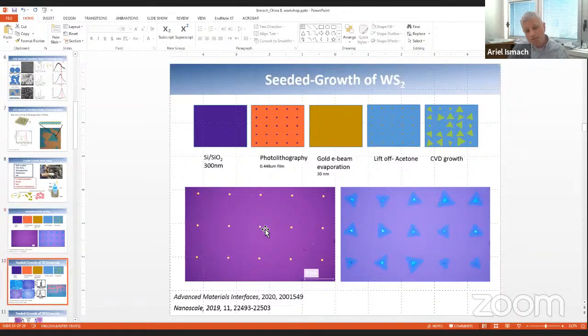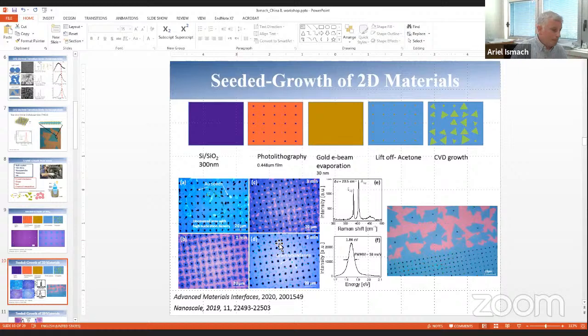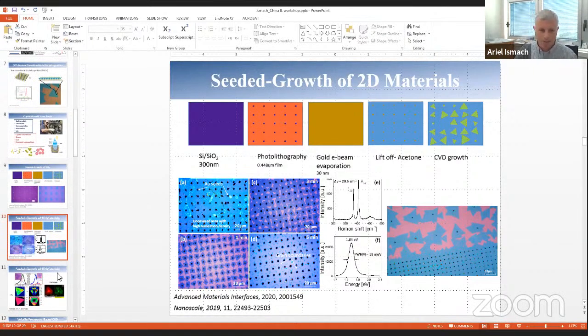So by doing that, you can in principle control the crystallinity of your film, because you can control the domain size of your film once you continue the growth and merge the domains. Here you can see an example in which, in the same sample, you have seeds that are separated by more than 50 microns, and seeds that are separated by 10 or 20 microns. And you can see the merging occurs only, of course, when the seeds are denser, because there you have higher nucleation density, which is basically the seed density. So this is nice, of course, and a few other reports were showing the same.